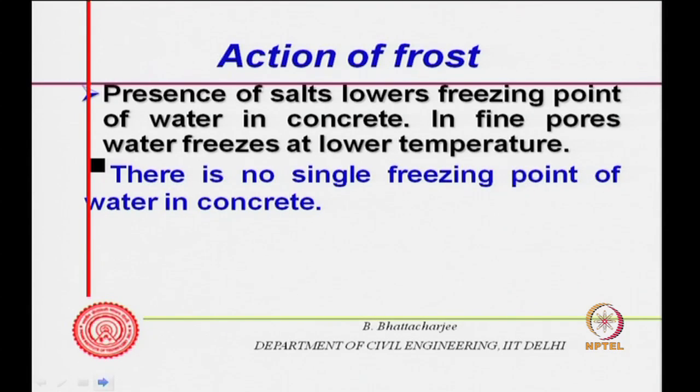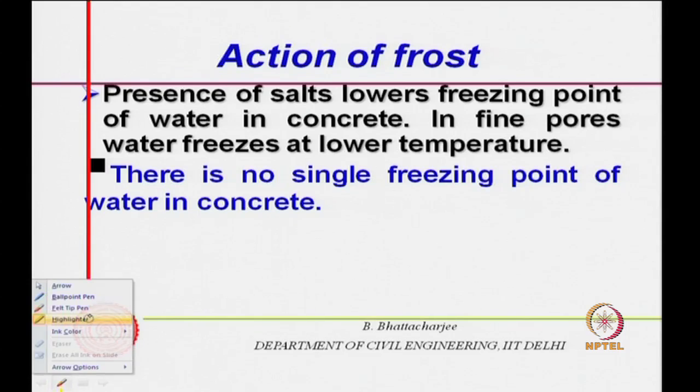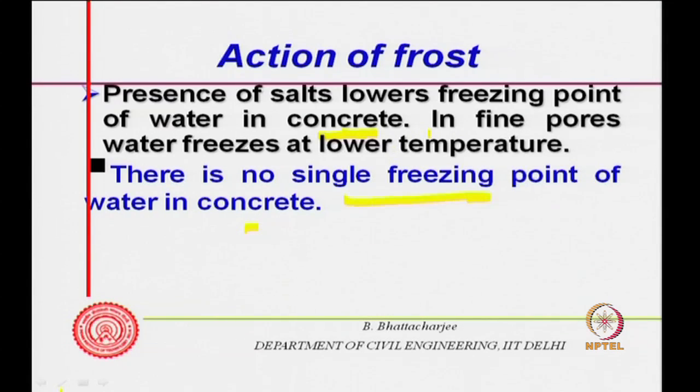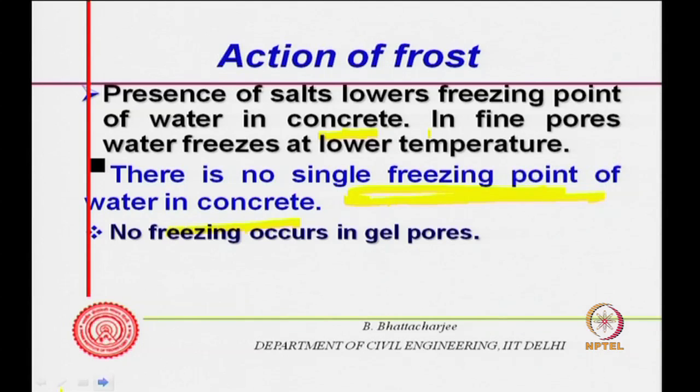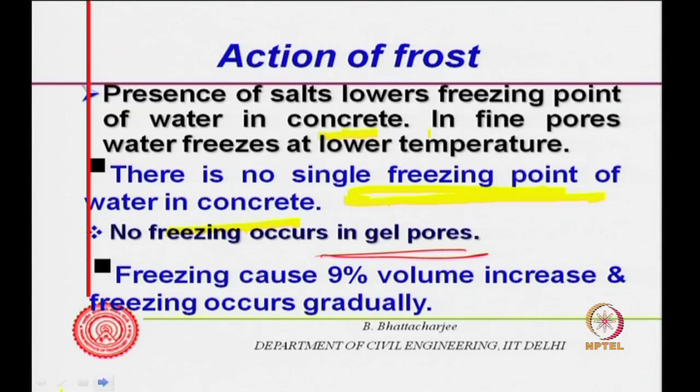Second issue is, since the porosity and pore sizes differ, salt concentration would differ at different locations in the concrete, so there is no single freezing point of water in concrete. And in gel pores, there will be hardly any freezing. No freezing occurs in gel pores. So, what it means is, even if the concrete is saturated and the temperature goes down, freezing will not occur simultaneously in all the pores. Only in some pores freezing will occur, depending upon the salt concentration, size of the pore, and of course, how close they are to the surface or freezing temperature.